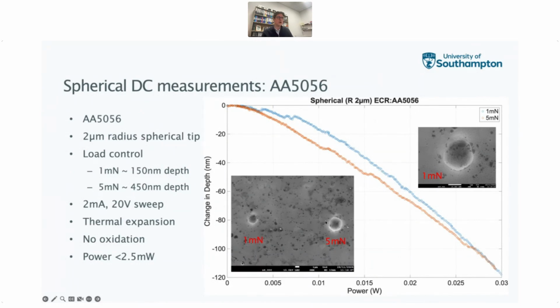We haven't got too much pileup going on here. We are assuming that we're not getting pileup when we do this sort of indent. And then we've swept through those powers again. So again, we've gone a little bit higher here to 2 milliamps and 20 volts. And you can see this thermal expansion occurring, as we've already seen. But the point is that if you then peer at the surface after you've done these indents, we're not actually getting any oxidation at the surface. It is just a thermal expansion effect that we're seeing, because we can still see the phases present in the material after we've done the indent.